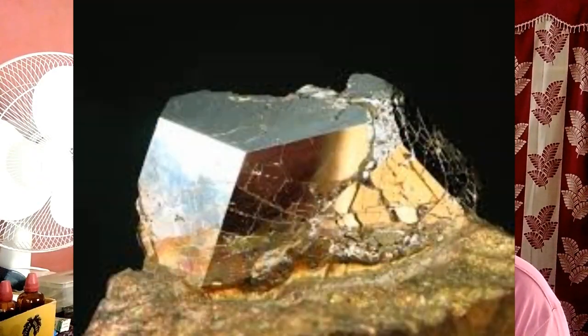Where fines or clays exist, the ore is agglomerated to create a uniform leach pile. The process consists of crushing the ore, adding cement, adding water or a cyanide solution, and curing in dry air for 24 to 48 hours.